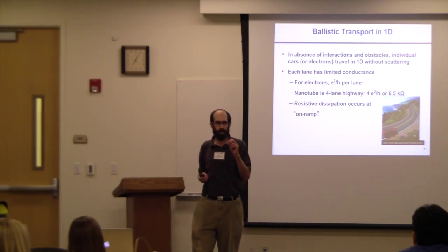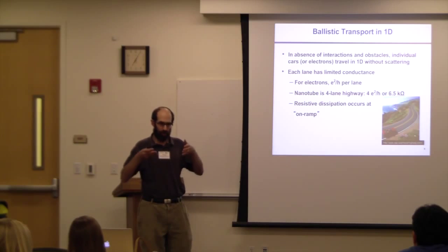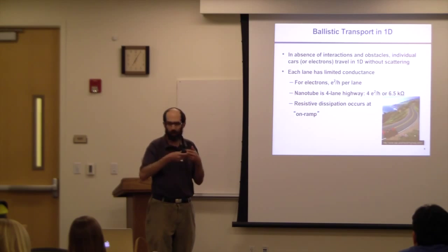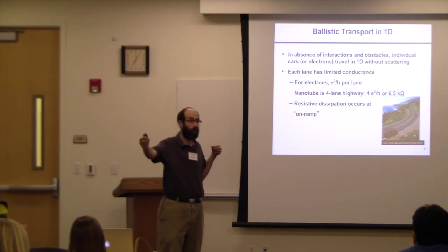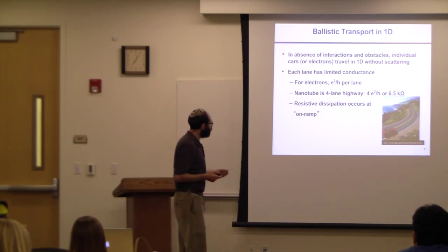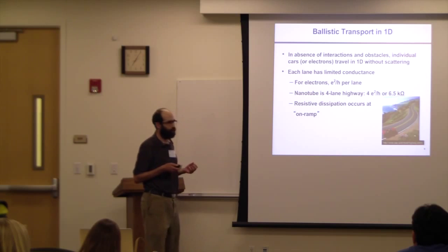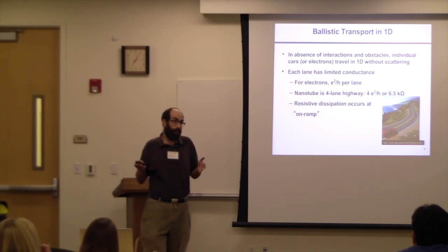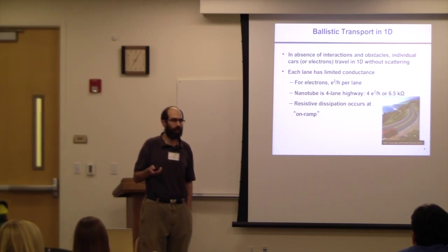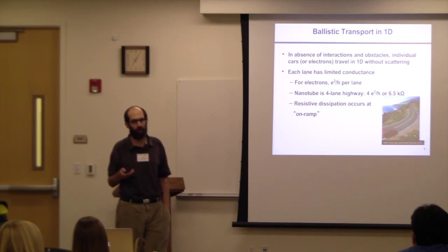So this 1 nanometer wire has a substantial resistance, and that resistance is all just getting into the wire and getting out of it. There's no resistance along the wire. We can make it as long as we want. There won't be any more resistance. And so that sort of gets you thinking, well, what if you could maybe pack a lot of these wires together? Could you do better than copper, which is pretty close to the best electrical conductor we have?